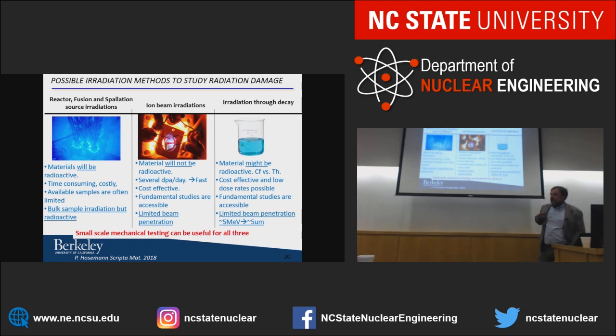But, of course, the material will be radioactive. That requires hot cells. That requires lots of dangerous work from students. And students get some dose on the film badges and things. Not so desirable. So you kind of want to have your samples very small in order to avoid getting students irradiated too badly. Or you can do ion beam irradiations. Ion beam irradiation is good too. But you typically have limited beam penetration. You cannot reach very far into the material unless you, again, make your samples radioactive.